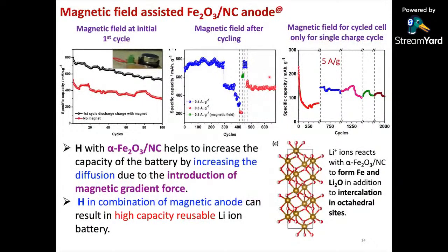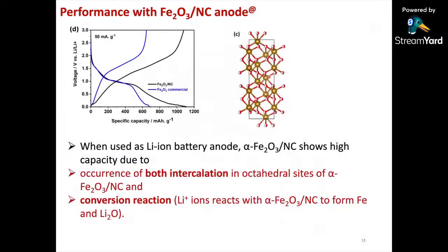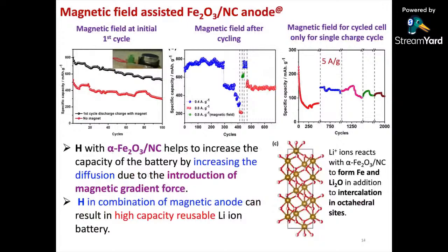Okay. Now we'll go to the magnetic field assisted Fe2O3/NC. This is in the absence of the magnetic field, and this is the performance we have obtained with the magnetic field. We just applied the magnetic field only for the first cycle charging, and then ran 100 cycles without any magnetic field. The anode is alpha Fe2O3 NC, and this has been applied with the magnetic field. You can easily see that the performance is more or less doubled because of the presence of the magnetic field.